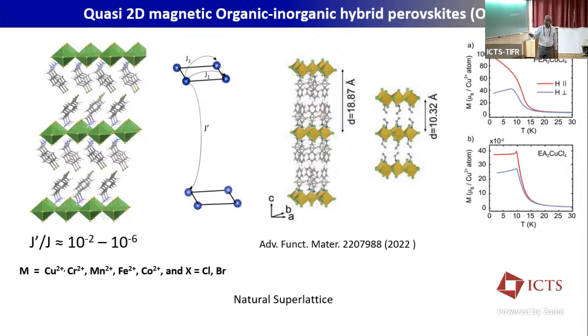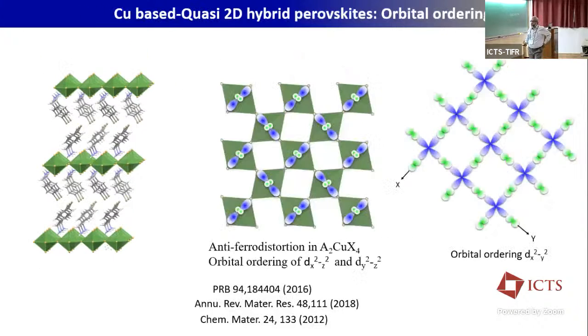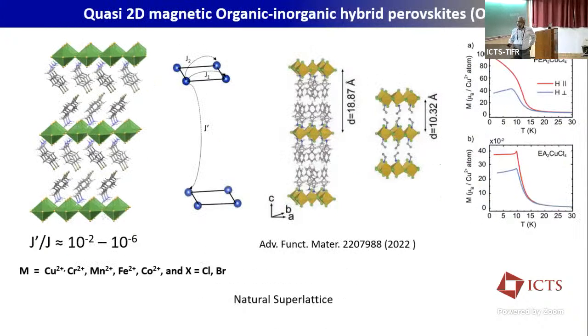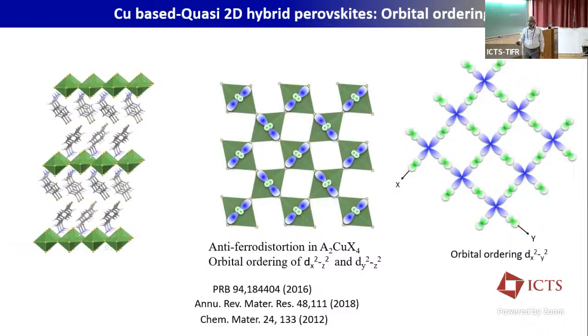Here you can see they've tailored this spacer layer. In one case they find roughly 18 angstrom, in another case around 10 angstrom, so that depending upon this spacer layer, your magnetic property completely changes. It shows a ferromagnet, but here you see there is a downfall in magnetization. As I mentioned, in these kinds of systems the magnetic ion can be transition metal based. But what I will be talking about is the copper based system, because copper based systems are more interesting for two reasons.